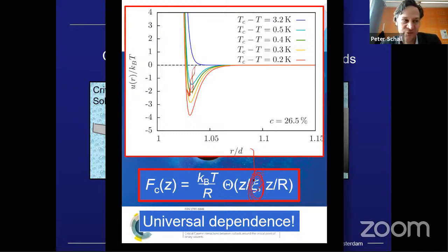So what you easily get, of course, already kinetically, at least that's what we see in experiments, is that instead of the 6 rings, you get 5 and 7 rings. And the 5 rings can be actually quite numerous, simply because you don't need the 6 particles, so kinetically you're faster in a 5 ring than in a 6 ring. And we do see that there are changes between 5, 7, and 6 rings. So there is diffusive attachment and detachment. This is what we have seen, and I think this is also characteristic in atomic graphene, but you know better actually.